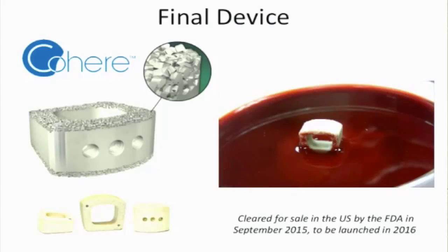Nice talk. In your opinion, what are the current challenges and limitations of shape memory polymers toward their use in biomedical applications as implants? I think the biggest challenge is when you thermally activate it, which is their best feature. We do a non-thermal activation; we let this gun trigger do it. When you thermally activate it, it does things to the polymer chemistry that make it weak long-term in water. That's one of the biggest challenges.